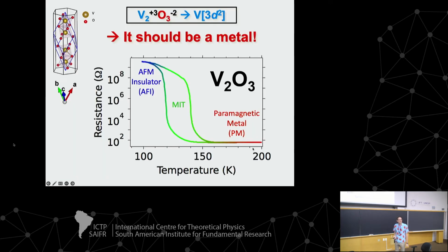V2O3. This is a system that, as a function of temperature, shows a metallic and an insulating state. Above something like 170 Kelvin, you have a paramagnetic metallic state. It is not evident from this graph, but resistivity actually goes down as temperature goes down. And then suddenly you have a 7 orders of magnitude increase of resistivity, and then resistivity goes up as temperature goes down, and you have a beautiful metal to insulator transition with a hysteresis cycle of about 20 to 30 Kelvin in width, okay? So this completely contradicts the standard model of condensed matter physics.